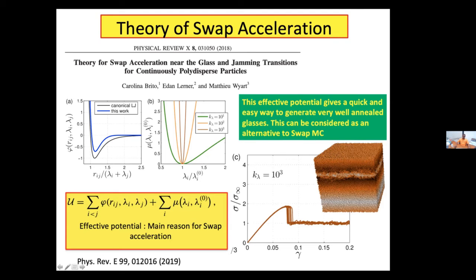And indeed, this is what has been done in this Physical Review E work of Idan and Matthew, where they did numerical work with this kind of potential, which allows the diameter of each particle to fluctuate within a certain window, and the spring constant of the potential is varied. This diagram tells you that for a spring constant of 10 to the 3, which is very large, the diameter fluctuation will not be very significant. Then you can get ultra stable glass just by doing a quench in this effective potential. So this gives you a new method to generate ultra stable glasses, and a new algorithm as well.